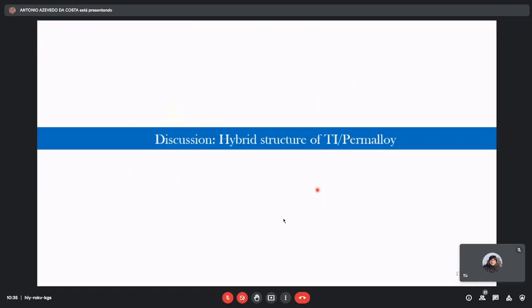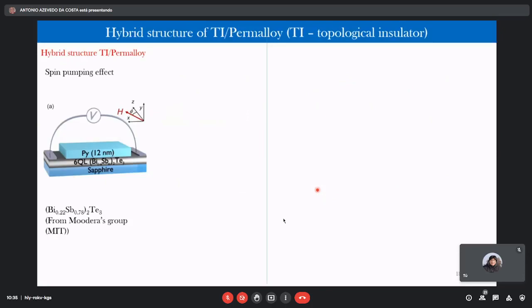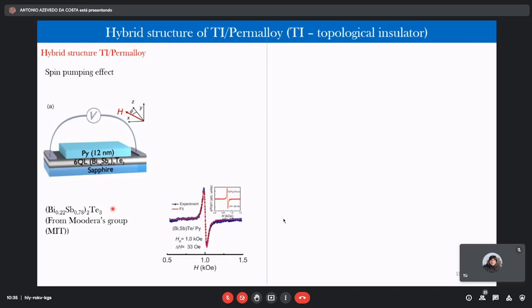And also, let's move to the next one. This is a hybrid structure made of a topological insulator and a permalloy. The topological insulator was fabricated by the group of Professor Jagadish Moodera at MIT. He is one of the experts in this kind of system, and he sent us some samples which are composed of six quintuple layers of this chemical composition here, and we deposited just on top of the sample an island of permalloy, and we also added two electrodes,